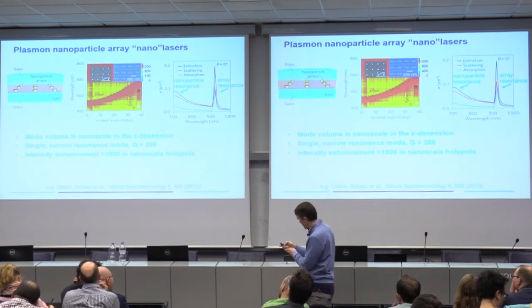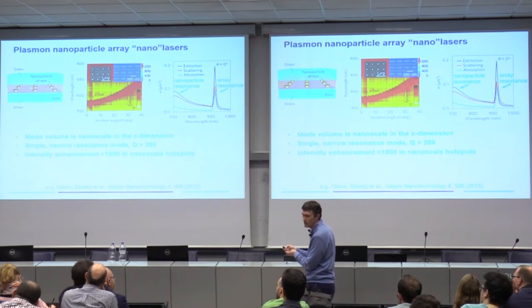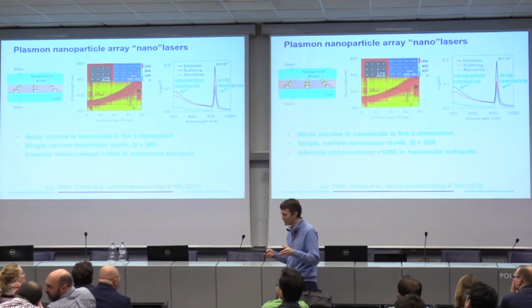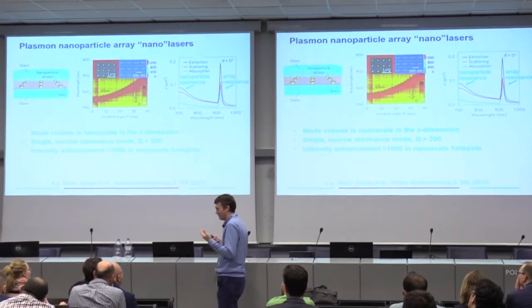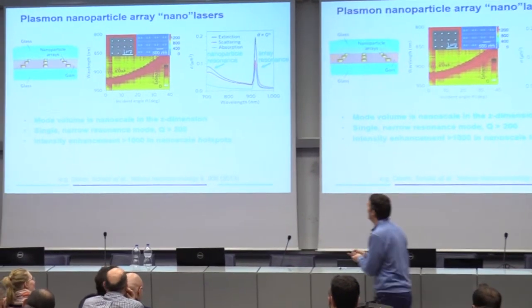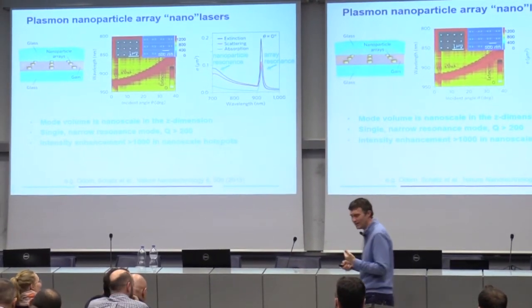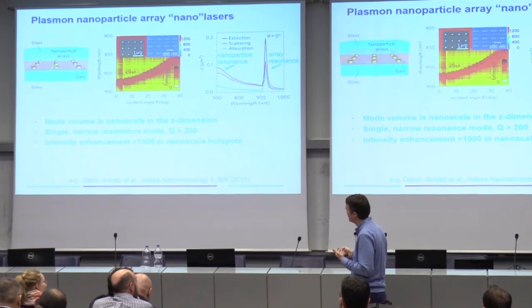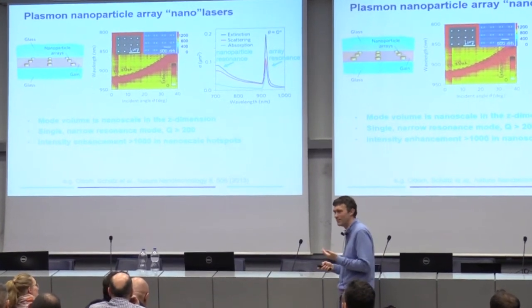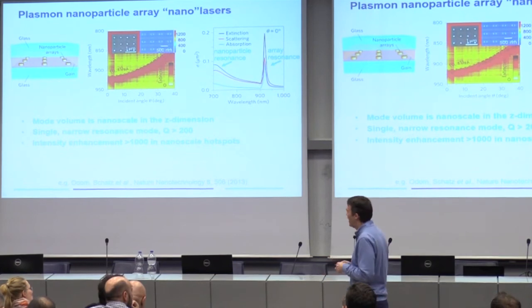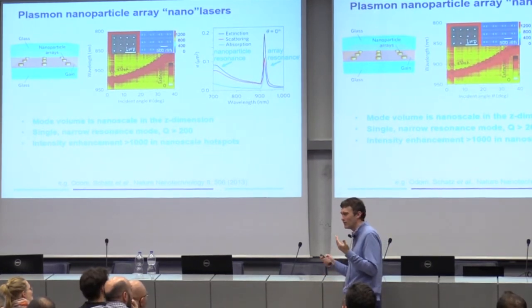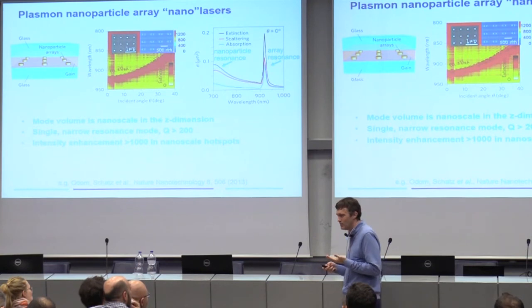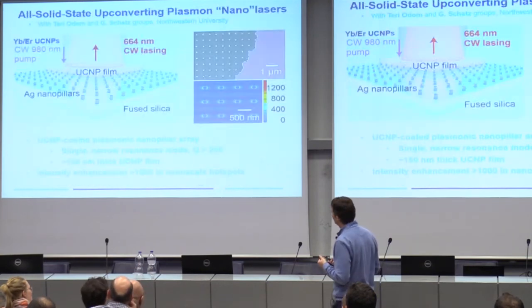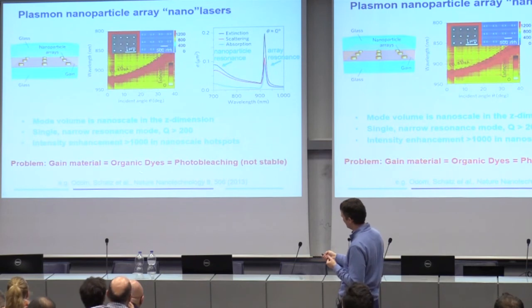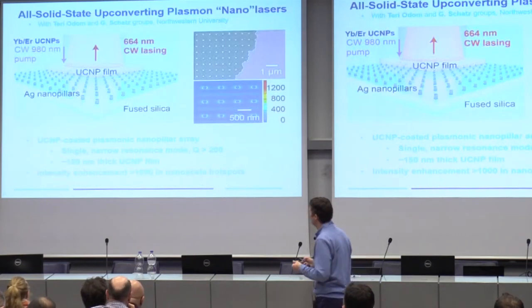These guys had already shown that you can make lasers, down converting, or down converting is the wrong word because that means something else, Stokes-shifted lasing, fluorescent lasers, I don't know what you call them. But you can get these things to lase. The problem is that the only gain material that really worked well in these was organic dye molecules, and that's bad because they photobleach. They don't last for that long. So immediately we started talking to them, and we're like, well, look, we might have a solid state solution to making your small plasmonic lasers. Problem: gain material equals organic dyes equals photobleaching. Right, bad. Okay, so here's what we made.